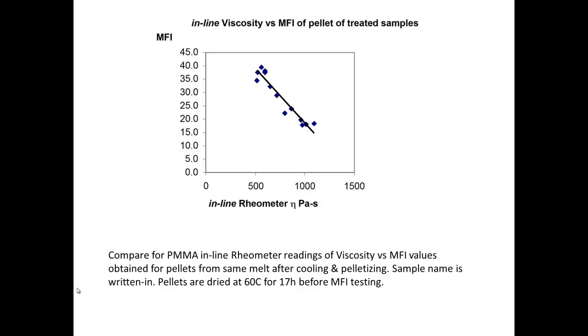And now we have succeeded in obtaining melts with various modifications of the MFI, and this is also observed in a melt which has various inline rheometer values, and you can see that I am at 500. That's the case I've shown you, but all the melts in between were also obtained and correspond to a value of MFI between 17 and 40.